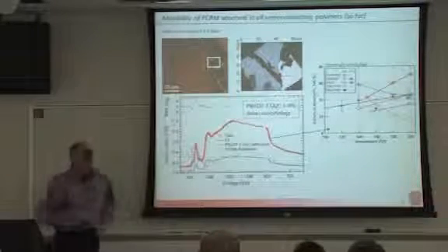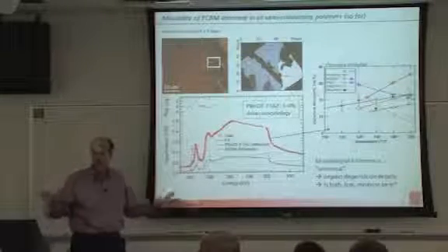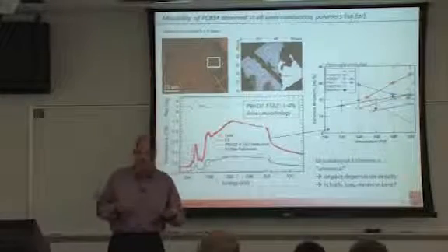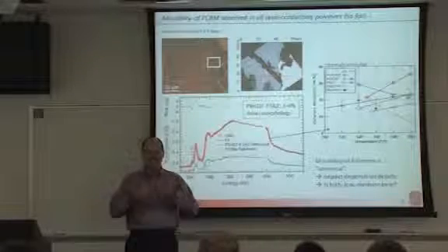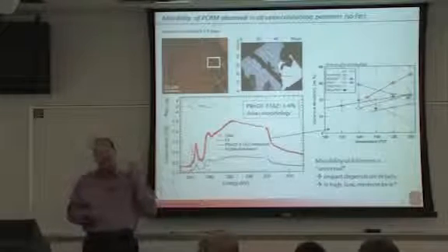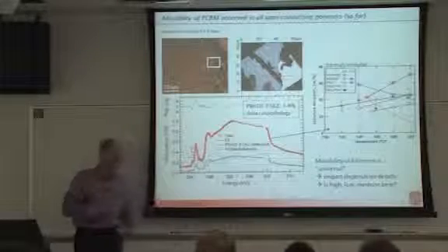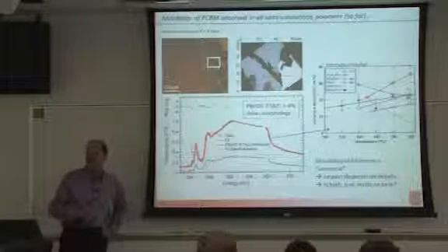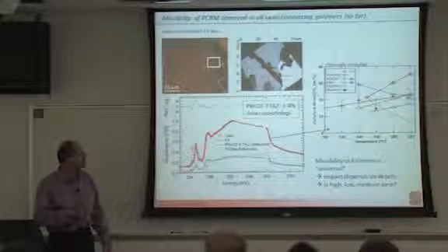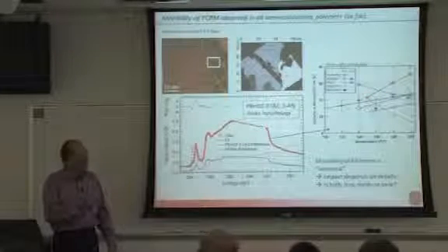Is that good? Is it bad? Do I want high? Do I want low miscibility? When I now do a chemical synthesis, I don't only have to worry about the HOMO-LUMO engineering, etc., solubility in a solvent. I also have to worry about the interaction with the PCBM in terms of miscibility or whatever interaction, chi, if you want to think of it in those terms, because that influences the phase morphology that you get in a device.